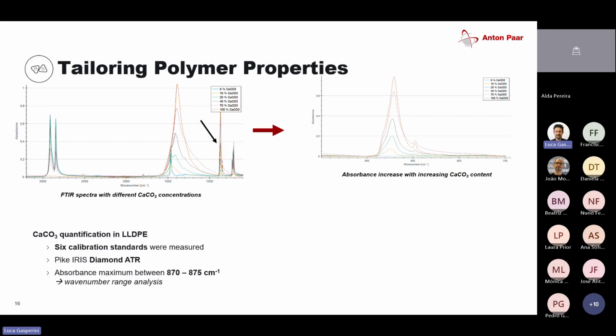So there's no peak at all. And then if I have 100% calcium carbonate, the peak is very, very high. And if I have different concentrations like 10, 20, 40, and 60, you can see that the peak is rising. So there are two possibilities. Either it's rising, so it gets higher, or it gets broader. So then we take a look typically at the integral area, or it can also do both.